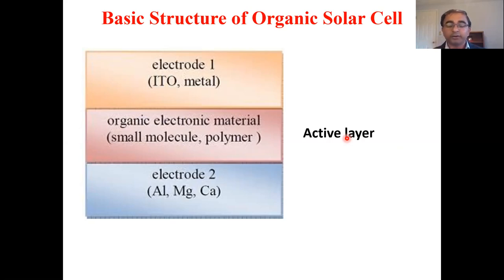Why is it less? Because in organic material, when you bring light on that, you might think electron hole pairs are directly generated. But in organic materials, excitons are generated. What are excitons? They are basically bound electron hole pairs. They are not free. And you have to dissociate this bound electron hole pair. Although the force needed is very less, you need an external force to dissociate it. And that external force is provided by the difference of electrostatic potential between these two electrodes. But the efficiency is very less.